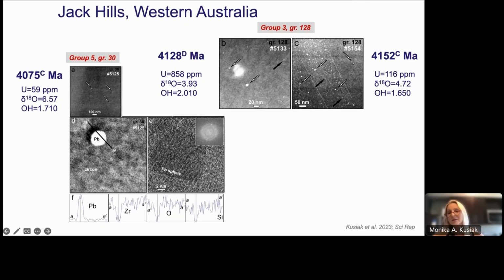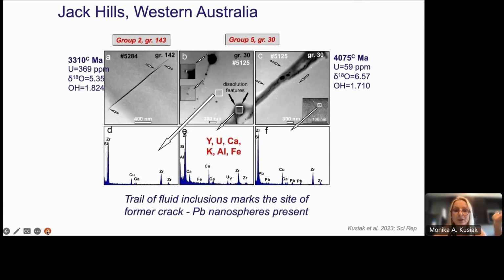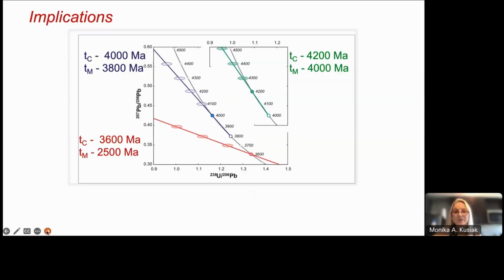This is still work which is going on, and we found that these grains had various cracks, and that lead nanospheres were present despite the cracks. So they are not connected with any fluid infiltration or cracks. This is a feature which is in zircon grains by itself. And I would like to show you what the implication of this finding is.